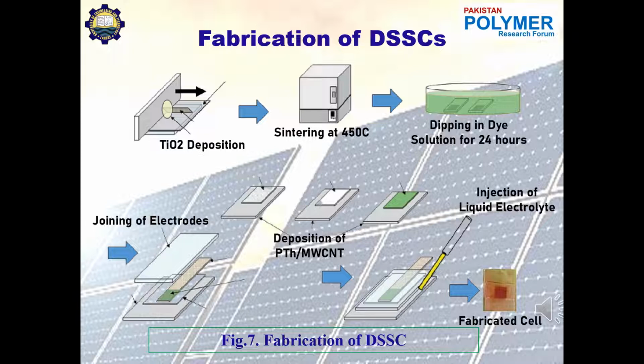After characterization of the nanocomposite, fabrication of the DSSC was done. First of all, titanium dioxide paste was deposited on the glass substrate, and the substrate was then sintered in the furnace at 450 degrees Celsius. The substrate was then dipped in the dye solution for 24 hours, and for the counter electrode, the polythiophene and MWCNT paste was deposited on a substrate with the help of the Dr. Blade method. Both electrodes, photoanode and counter electrode, were joined, and liquid electrolyte was injected through a dropper or syringe, and the fabricated cell was obtained.